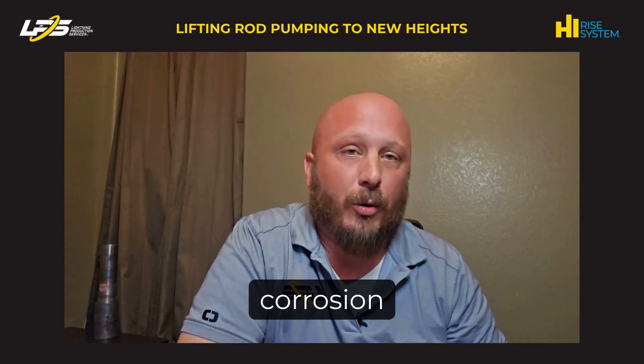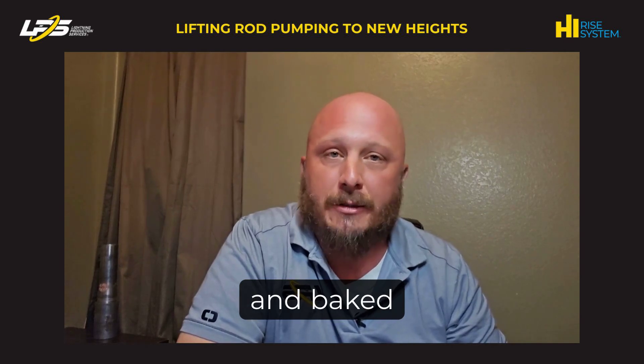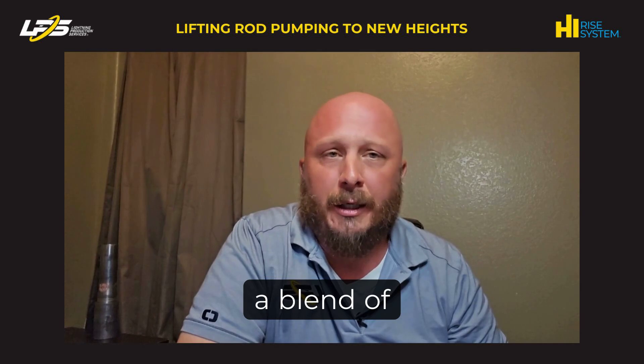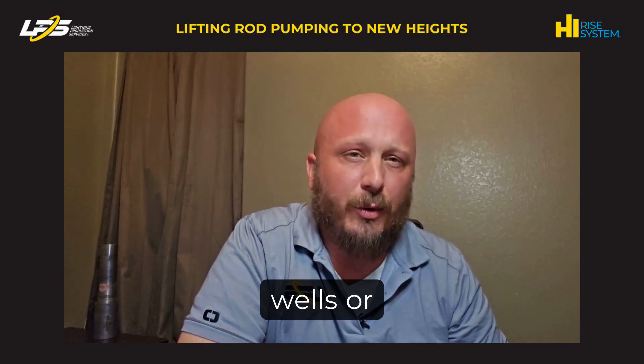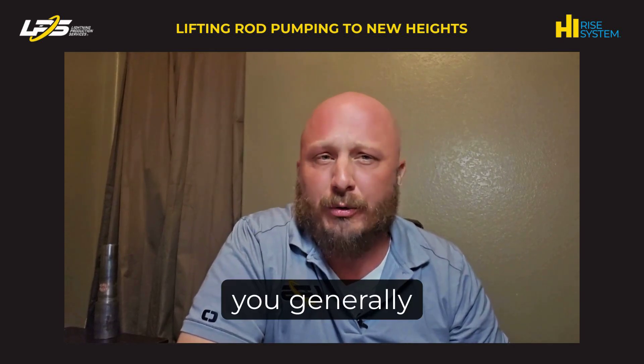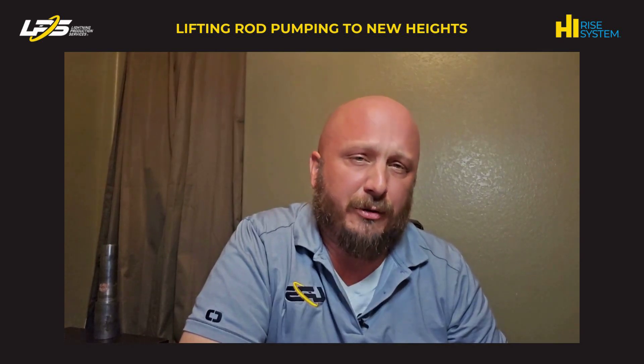IPC products are designed to handle corrosion and wear to a degree. IPCs are sprayed on and baked on, they're generally very thin — 8 to 12 mils thick — and typically a blend of different epoxies. They tend to be used more often in corrosive wells where ID is of importance, and you generally see IPC tubing in wells with most forms of artificial lift.